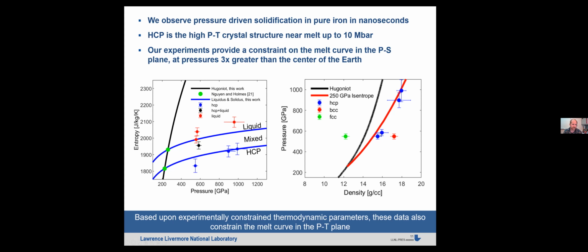And then I also wanted to go through the justification for HCP. So beyond the fact that we see a triplet, some of it was textures. So you can say, well, what is the source of those spots? We can also look at this data in the context of what the equation of state should be. If we tried to interpret, say, the strongest line as being from the BCC 110, or the two strongest lines as being from the FCC, if you try to interpret those diffraction signatures as being from BCC or FCC or any reasonable candidate, they're inconsistent with the equation of state of iron, whereas interpreting that diffraction data as being HCP is consistent with the equation of state. So again, we find that HCP is a high pressure temperature crystal structure of pure iron near the melt curve up to 10 megabar.